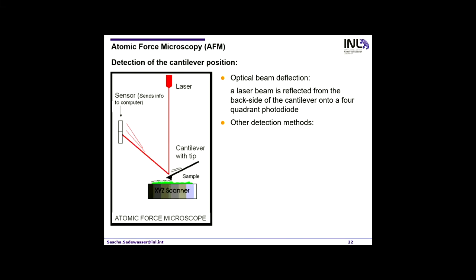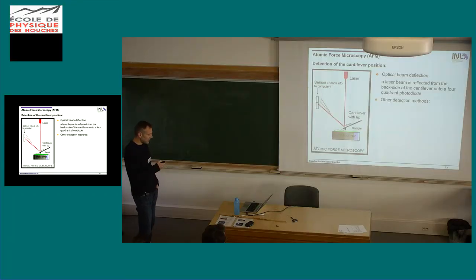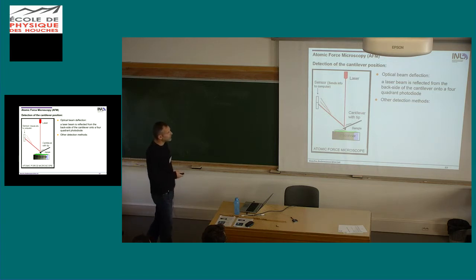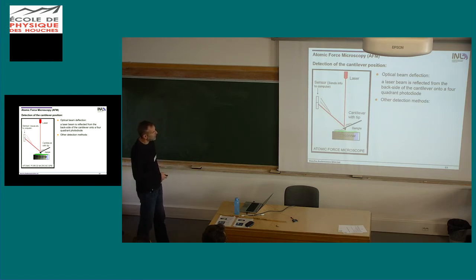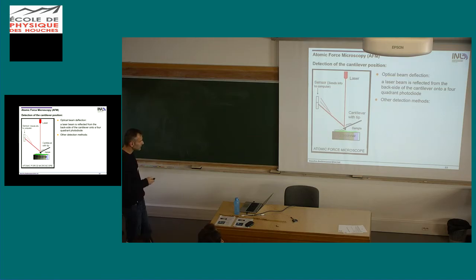And instead of using an STM on the backside of the cantilever, nowadays what's most common is to use a laser. So you shine a laser onto the backside of the cantilever, which is reflected to a position-sensitive photodiode. So these are four small photodiodes, a four-quadrant photodiode, to measure how the beam is deflected on the backside. And of course, you know this very well, a small movement here makes a big movement over there, so you're very sensitive to small movements of the tip with this.